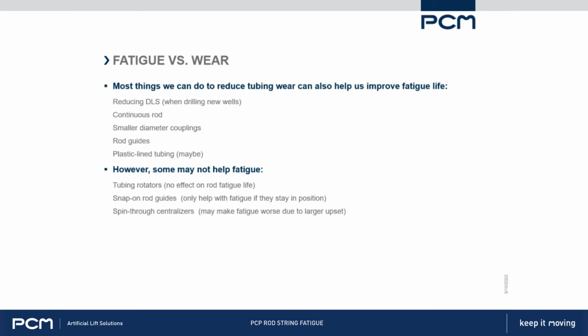If you're using a tubing rotator, they're great for reducing wear, probably give you 3 to 5 times the life of your tubing string. It has basically no effect at all on fatigue life. So you've solved your wear problem. Now maybe the fatigue problem is going to be what you see first. So it's a good idea, absolutely. If you've got high tubing wear, you want to run a tubing rotator, but you do also need to think about your fatigue life as well.